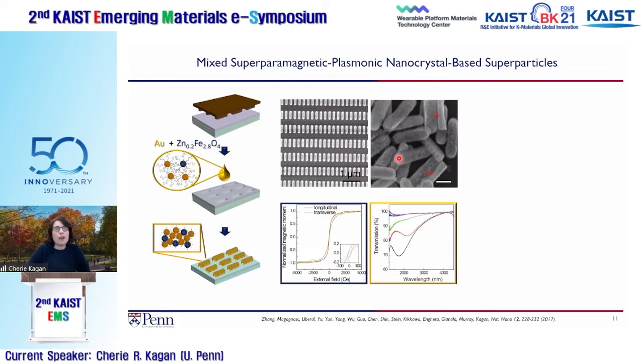And so what we found is that if we do that ligand exchange, the magnetic oxide materials don't like to fuse in the same way. Even after that process, in these rods you see in their magnetic characteristics a nice, tall hysteresis loop. There's a large magnetic saturation, this one's normalized, but you can see that there's no coercivity.